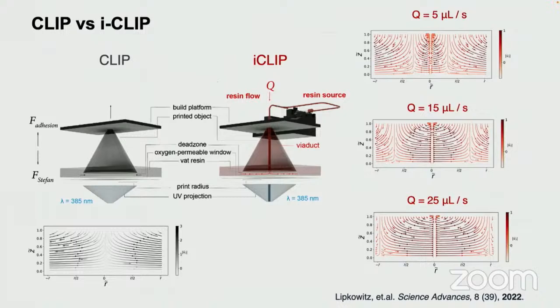And what's fun is you can basically toggle some gradient between CLIP and iCLIP. Imagine building a part where you fed 20% of the resin via the channel and 80% was drawn in from the periphery. Or you fed all the resin via the channel. And so you can run this process. Here's an example where all the resin needed for the part is coming through that central port. Well, here is where we're delivering just a fraction of the resin through the central port, and some is coming from the periphery, and you get a stagnation zone underneath the part, which has some really beautiful fluid mechanics interface at the stagnation zone, and you can toggle through that.